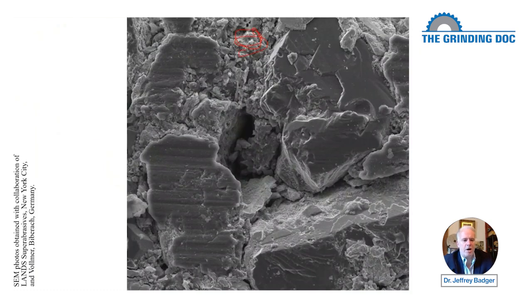What we see is bond material and loading in here, okay? And then what we have here is a nasty flat grit. That's actually probably not a dull grit, but this one right here is. You can see the direction of grinding right here. And what we have is that nasty dull grit. And grinding with a dull grit means a lot of rubbing, a lot of heat generation, huge normal forces, and cracking of the CERMET possibly if things get hot enough. It just means general unpleasantness, okay?